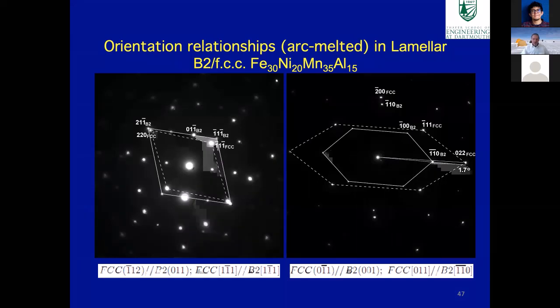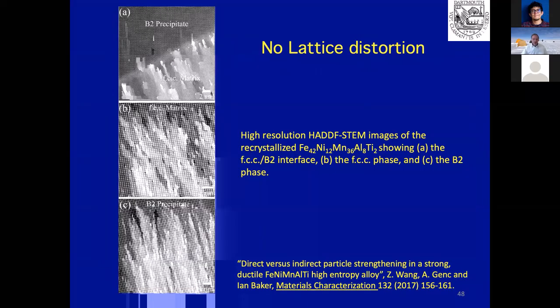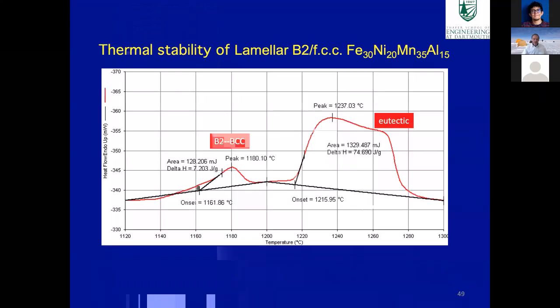If you look at the diffraction from the two phases together, we find that actually there's a Kurdyumov-Sachs relationship between them, which is often seen between BCC and FCC phases. If we do some lattice imaging from the material, we see these very nice lattices for the two and a very clean interface between them. And one of the things we found is there's no particular lattice distortion. All these planes line up very clearly.